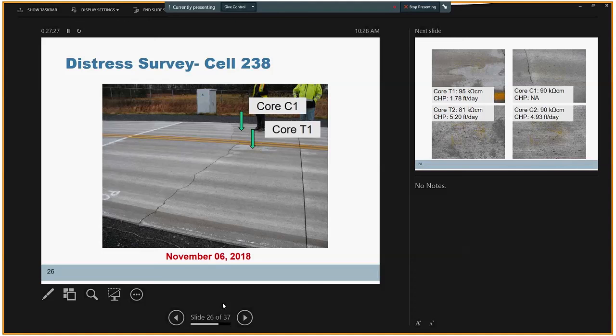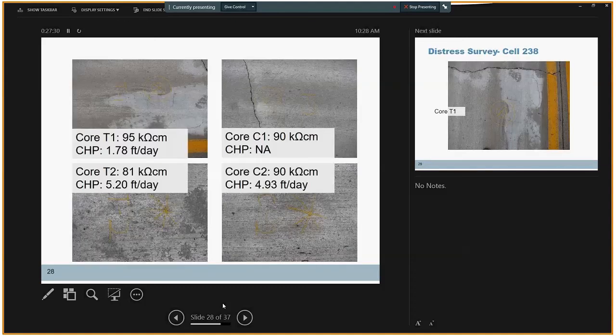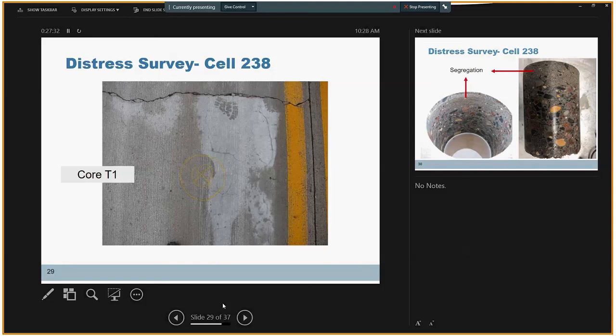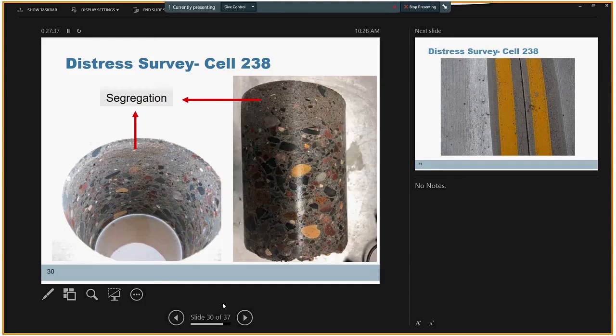But it was interesting to see that in one of the core locations where we had the main distress, there was a segregation of concrete, even in concrete with lower cementitious material of 470. The cores are under investigation right now. We are measuring the resistivity, and we are trying to take a look at the concrete properties here.